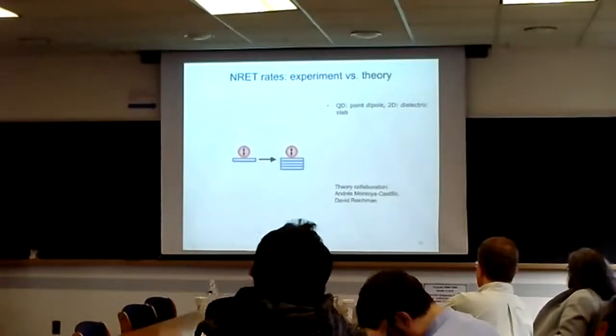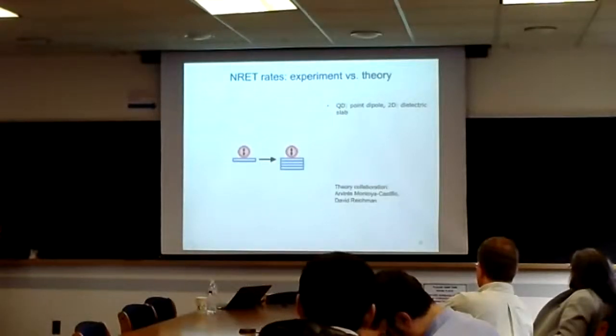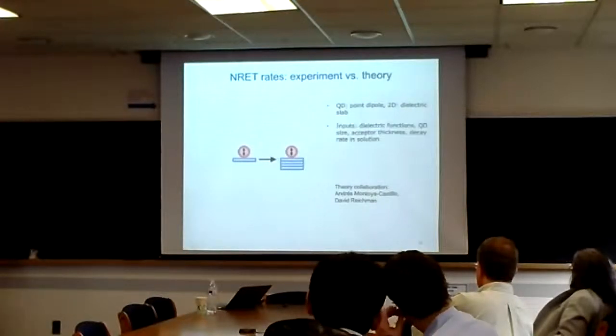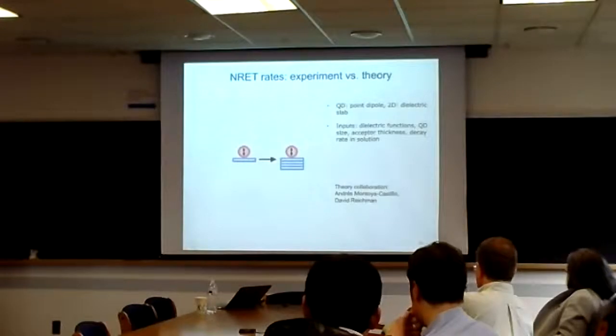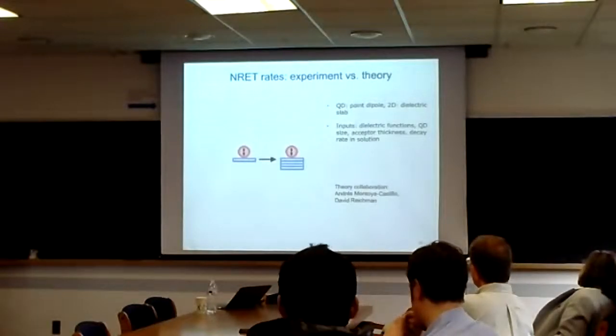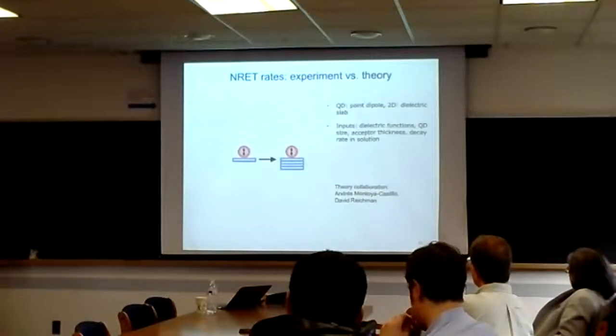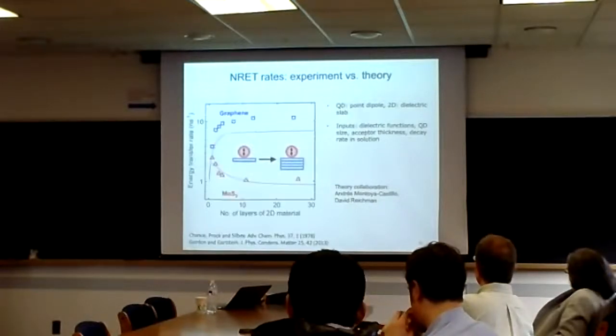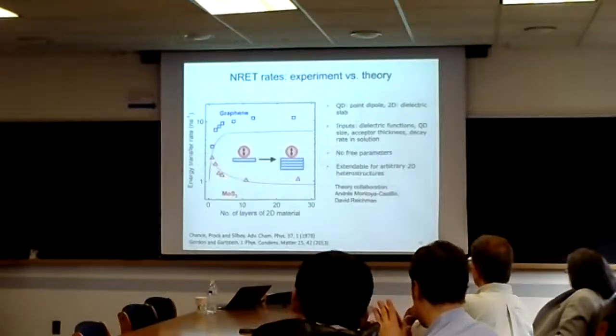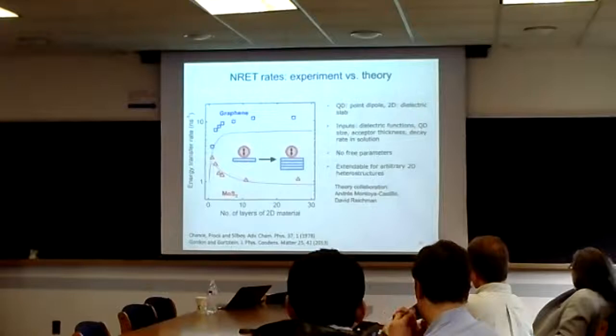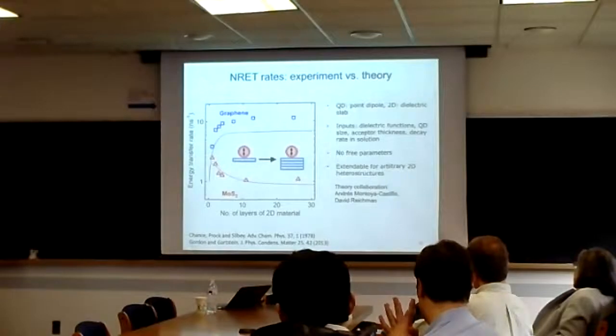So actually, we collaborated with David Reichman's group again in this case, and we treated the quantum dot as a point dipole, and the dielectric 2D material is just a slab. It's very classical in that sense, and the inputs were just the dielectric function, the quantum dot size, and the acceptor thickness, and using the decay rate in the solution, we can just get the numbers out. There are no free parameters here. This theory was originally developed by Chance, Prock, and Silbey in the 70s, and more recently adapted here for 2D materials. And what we see is remarkable: within a factor of 2, not only the trends, but also the absolute rates.